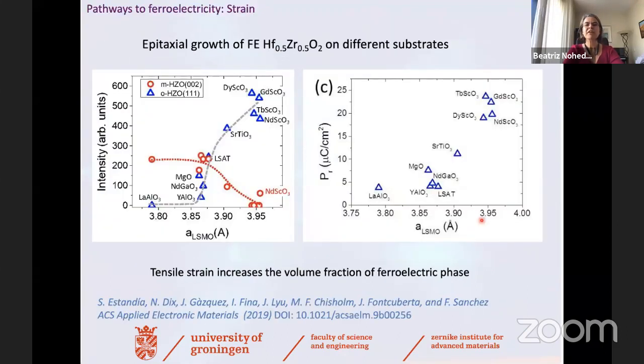Epitaxially grown hafnia was also done in the group of Florencio Sanchez and Josep Fontcuberta at ICMAB, and they have grown hafnia on different substrates and looked at a very important correlation between the polarization of hafnia and the strain, the epitaxial strain on the films.